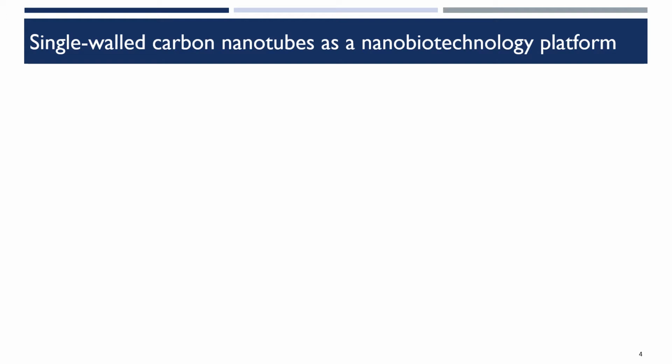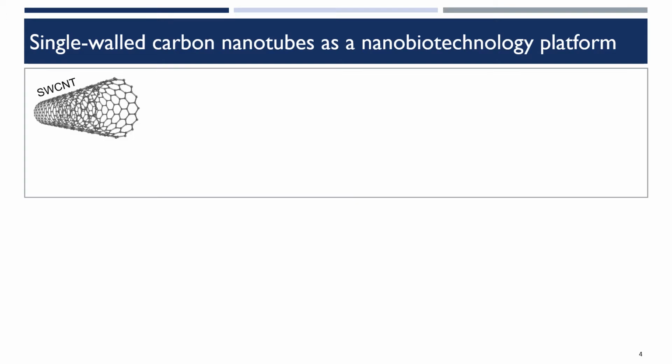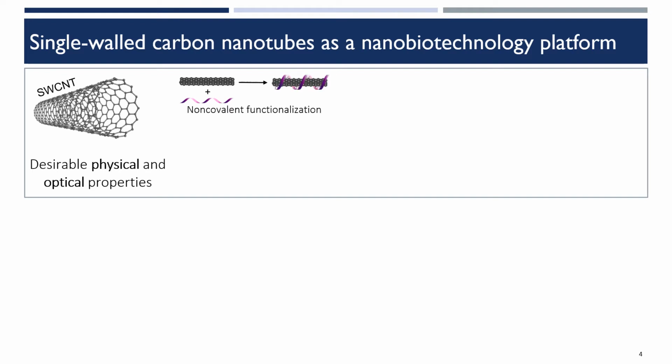I want to begin by introducing carbon nanotubes as a nanoparticle possessing unique physical and optical properties for nanobiotech applications. Carbon nanotubes exist on the nanoscale, and their high aspect ratio provides a large surface area upon which we can load functional cargoes for delivery or sensing moieties to build a nanosensor. However, these nanotubes are composed of all carbon and are therefore extremely hydrophobic. To apply these nanotubes in aqueous bioenvironments, we employ non-covalent surface modification with biomolecules and polymers.